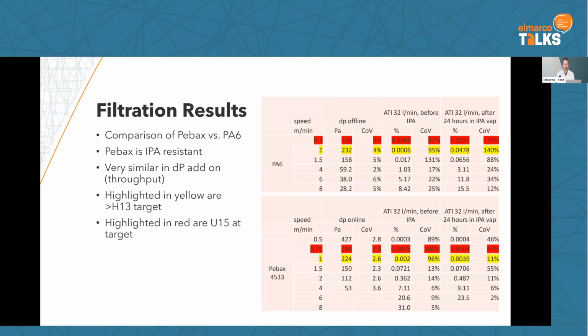If we want to look at some initial filtration results, and we compare it again to nylon 6, you can see that, if you want to start looking first at the results before and after discharging, what we do to discharge is IPA. It's related to ISO standards, where you want to make sure that once the material is exposed to humidity or anything like that, the material doesn't discharge and lose its efficiency. So we use IPA, and we simply put these in an IPA vapor for 24 hours.